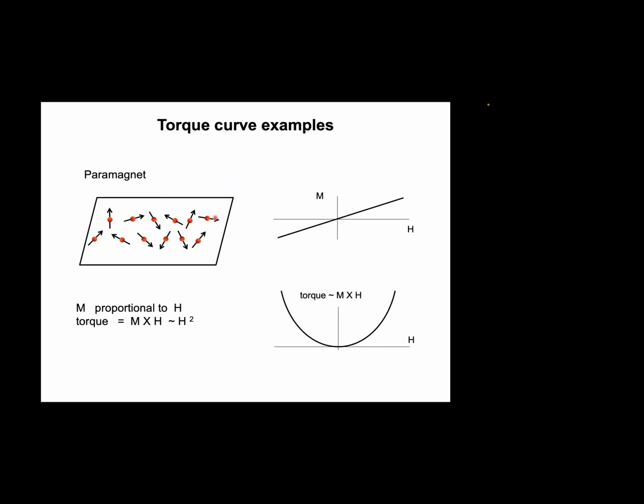We're going to look at a paramagnet to start with. For a paramagnet, M is proportional to H, so it's just from the polarization, right? The torque, which is M cross H, is linear times linear, so we will have a quadratic dependence. That's what the majority of compounds show at very low field. Turns out that's indeed what we observe out of this compound. It's a paramagnet.